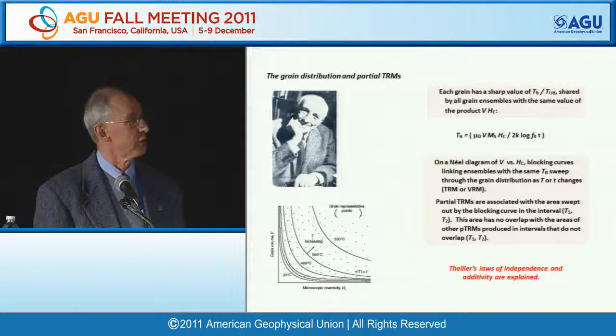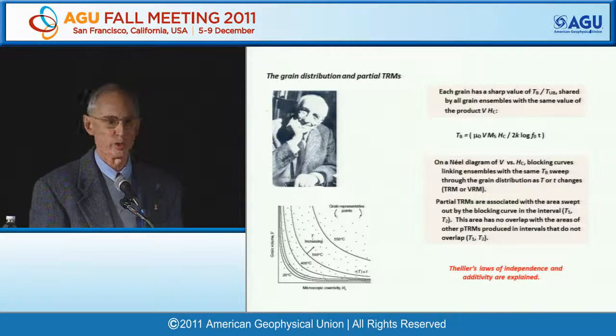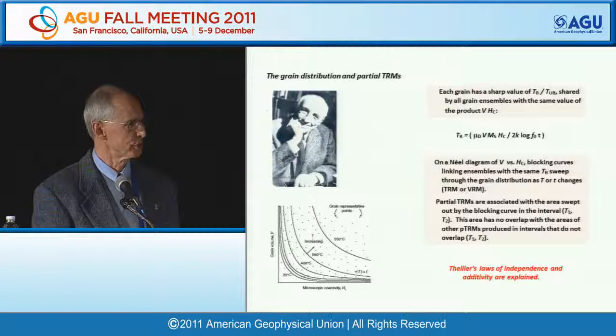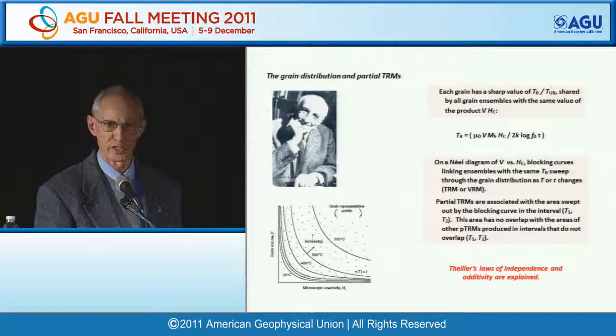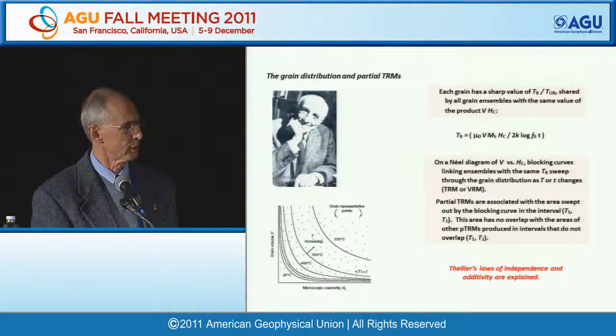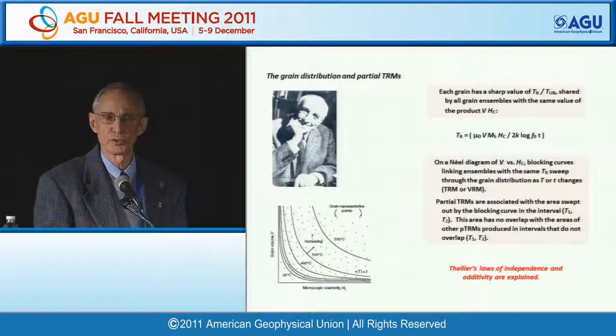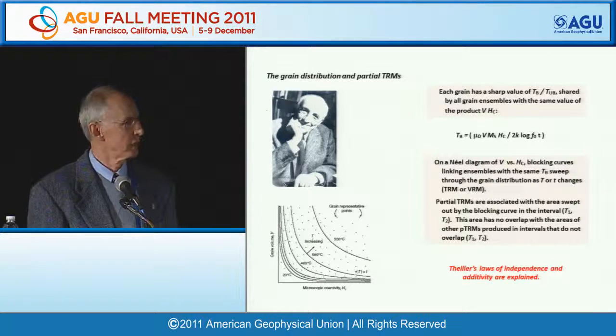Now, each grain has a sharp value of the blocking temperature, but it's shared by all the other grain ensembles that have the same value of this product, VHC, because that's the combination that occurs in the equation for relaxation time. Néel then invented this useful diagram of volume versus coercive force, in which all ensembles with the same value of VHC, and therefore the same blocking temperature, are linked together along this hyperbola. Change the temperature, and the hyperbola moves through the grain distribution of all ensembles, either magnetizing or demagnetizing the grains.